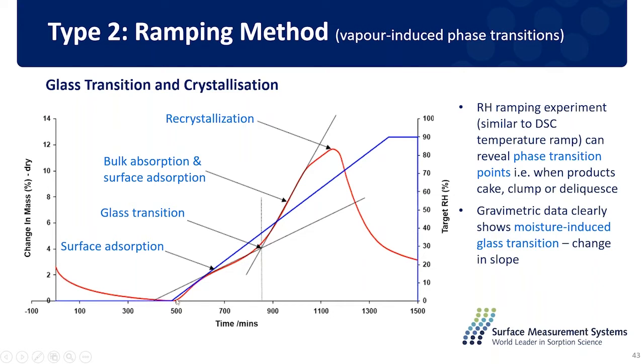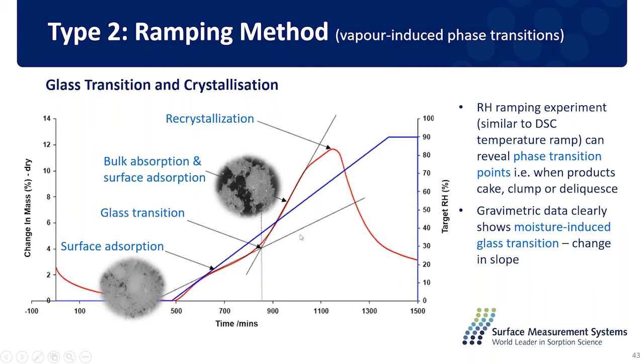And we have the red line here for the mass change of the material. What you can notice is that during the drying step it is losing mass, and when we start introducing the moisture, it's picking up the moisture very slowly. That's because just the surface sorption is happening here. After a certain point of humidity, the water uptake will increase dramatically because the water is not only on the surface, but also penetrates the surface and goes to the bulk. So it's a bulk sorption dominated mechanism happening here. There will be a slope change between the surface sorption and the bulk sorption, which accounts for the glass transition. So from this plot, we can calculate the glass transition humidity of this sample at 25 degrees.